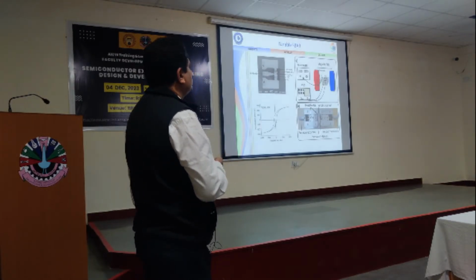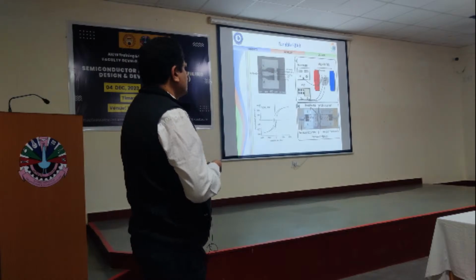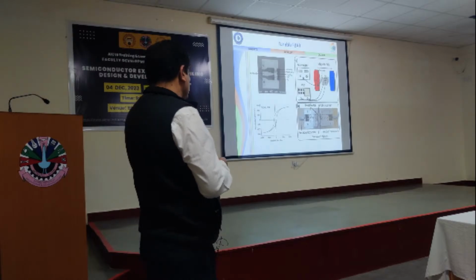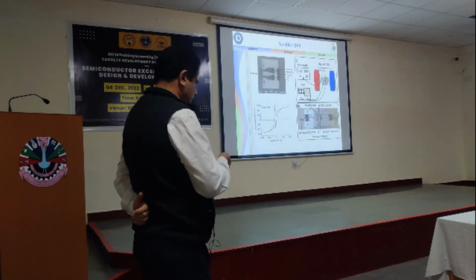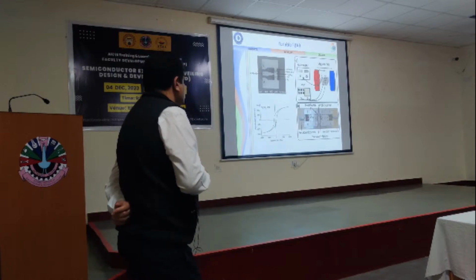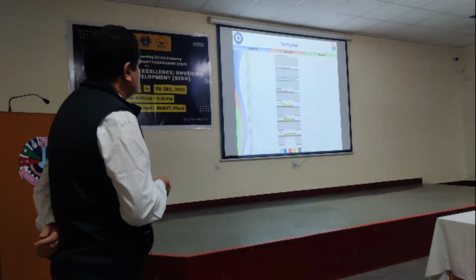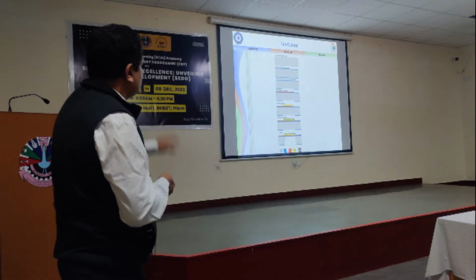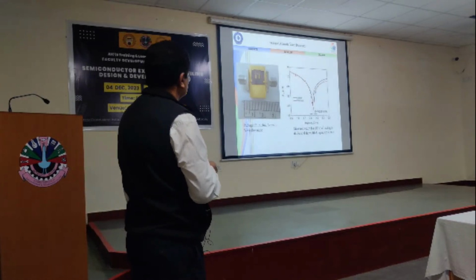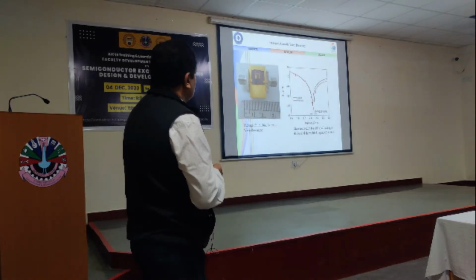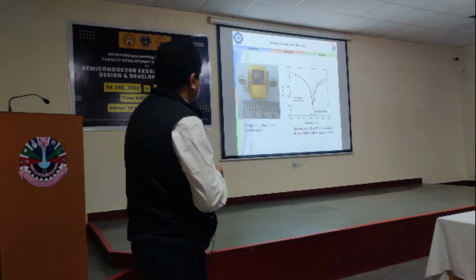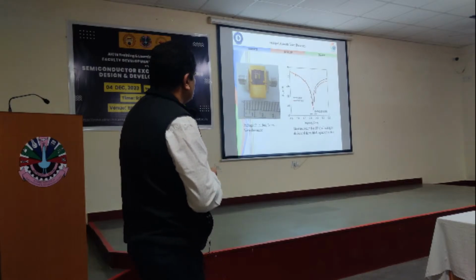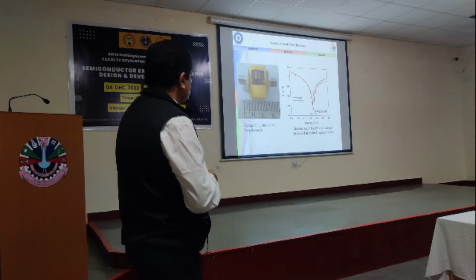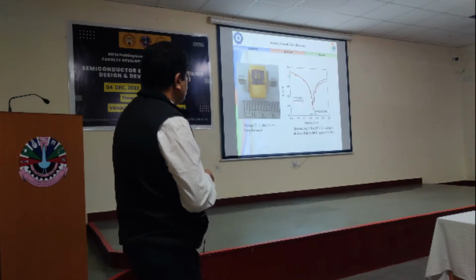Then we do some other measurements also of this, its magnetic performance, its sensing performance, and some of the calibrations of it. Some of the hysteresis loops of the magnetic materials we measure. Processing already we discussed. Some of them we utilize for the magnetic sensor applications by integrating magnetic layers, and we see the response here when we have no field, when we have with field. So there was a shift in the resonance frequency.